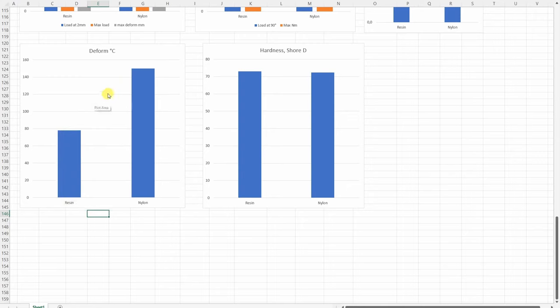until maybe 78. I tried to analyze the time-lapse footage frame by frame, and the nylon, well, started with deformation, which I noticed at approximately 150 degrees Celsius. And I always measure the hardness, and maybe once I will know how to use this information.